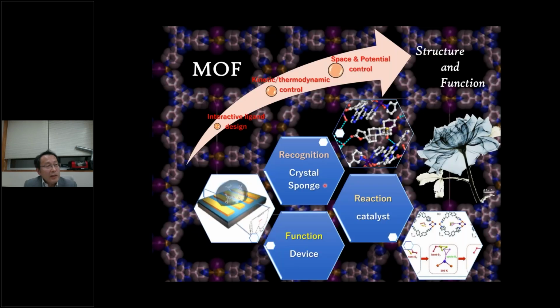So the next slide summarizes our recent research interest. Actually, we are interested in the metastable structure of a MOF. So then, how can you generate such a metastable structure? We pay attention to the interactivity of a ligand. If you use an interactive ligand for MOF synthesis, you can easily trap the metastable state. That means you can deepen a local minimum potential well. In this case, you can easily isolate only the kinetic phase. That's why we started designing interactive ligands.